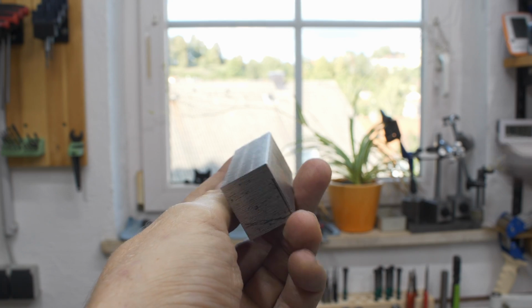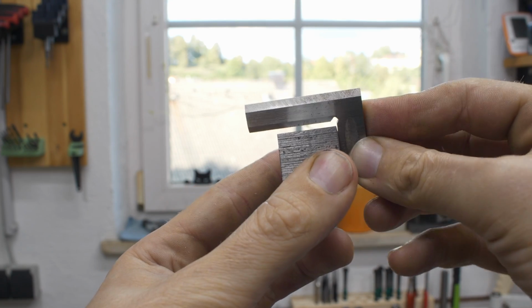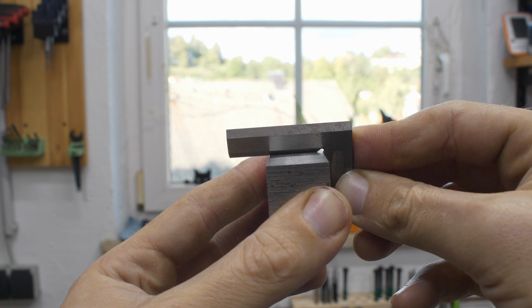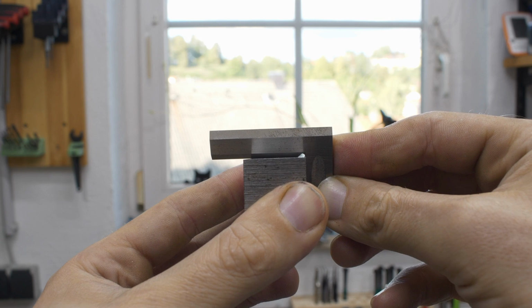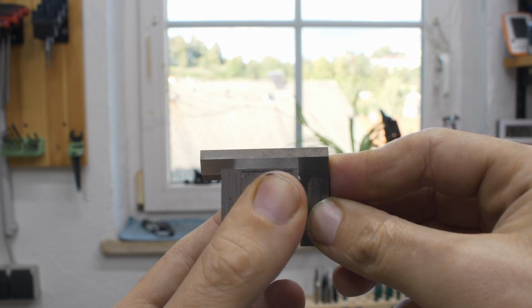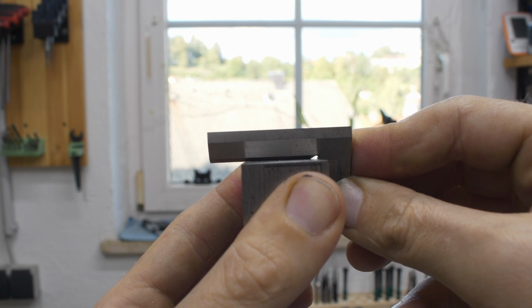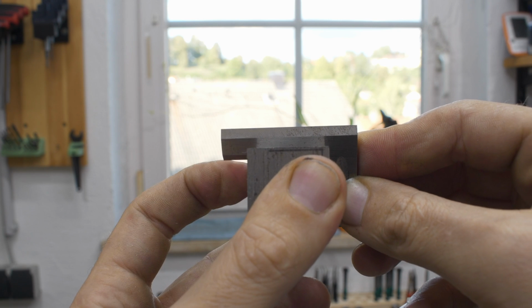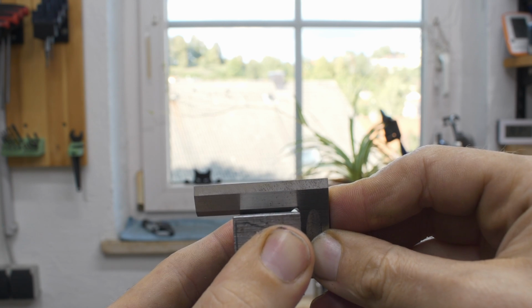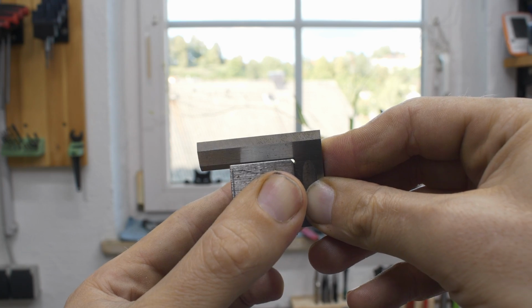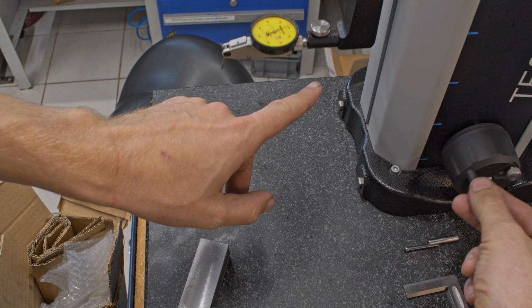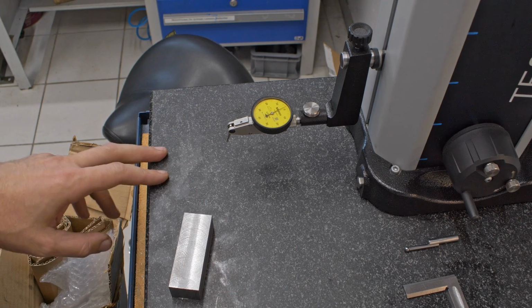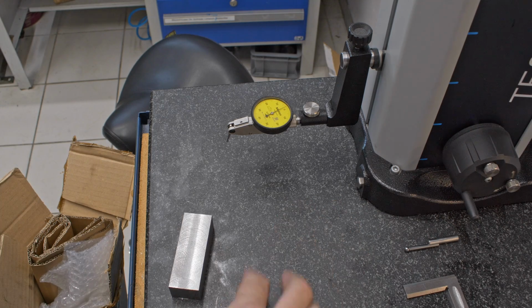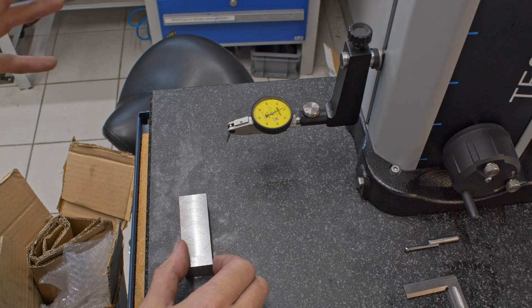Okay, right off the milling machine, let's check with a square against a light gap. It's hard to tell in the video probably, but this is really not terrible for right off the mill, using a fairly large cutter with a little bit of cutting pressure. It shows a little bit of light over here on the left side, but we can qualify this in a second over on the surface plate using the height gauge. I have a 10 micron reading indicator mounted to the measuring slide of my Tesa height gauge, which has squareness tolerance to the surface plate of 2 microns something over 400 millimeters. So this can be used extremely well as a squareness checking device.